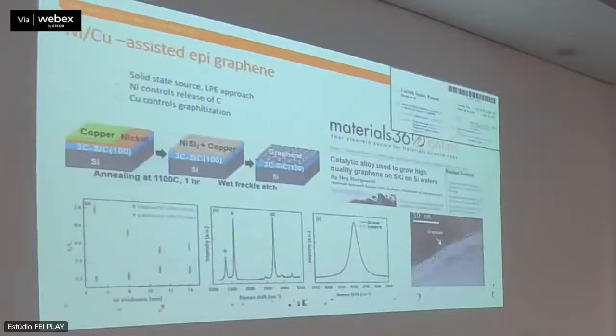Which is not actually what we do here, because, very importantly, I forgot to say, this growth happens in a liquid phase. So we usually grow at 1100 degrees, and 1100 degrees and above is liquid. Silicides are liquid as well. And so what happens is that as this process grows, the amount of nickel will be linked to the amount of carbon. And all of those byproducts will be floating.